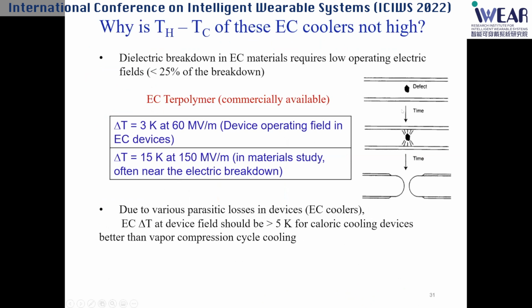The reason is very simple: in all practical devices, we have to consider electric breakdown. When we do measurements and publish papers at the university level, we usually measure the performance at the highest electric field we can. Let's say in this case we put 150 megavolts per meter, we can get 15 degrees at the top. But in a practical device, the electric field you can apply really should be at least 25% below that breakdown field, so that you can have reliable device operation. So in this case, for the terpolymer, this means you can only work at 60 megavolts per meter, and at this field the temperature change is only 3 Kelvin.